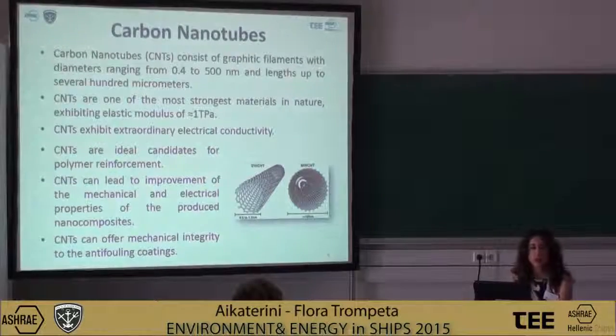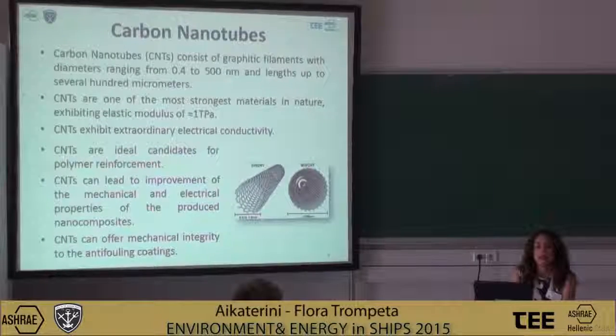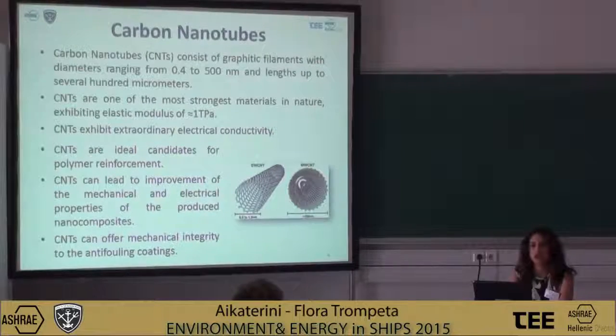Carbon nanotubes are an advanced material that has been developed in the last decades, and they consist of graphitic filaments with diameters ranging from 0.4 to 500 nanometers, a length up to several hundred micrometers. Their structure is presented at this photo. CNTs are one of the strongest materials in nature, exhibiting elastic modulus of about 1 terapascal. They also exhibit extraordinary electrical conductivity. That means that they can be used also for electronic applications.